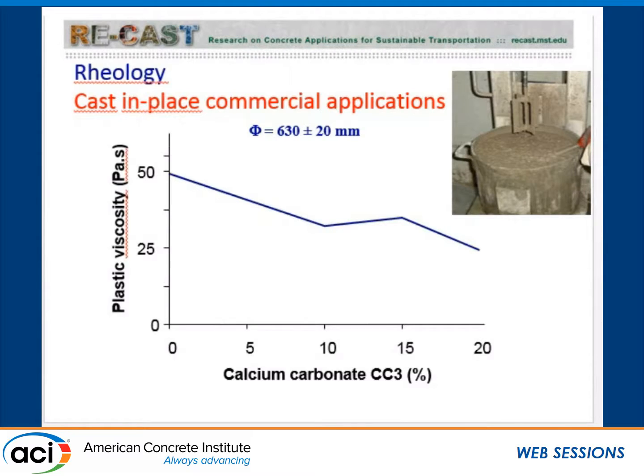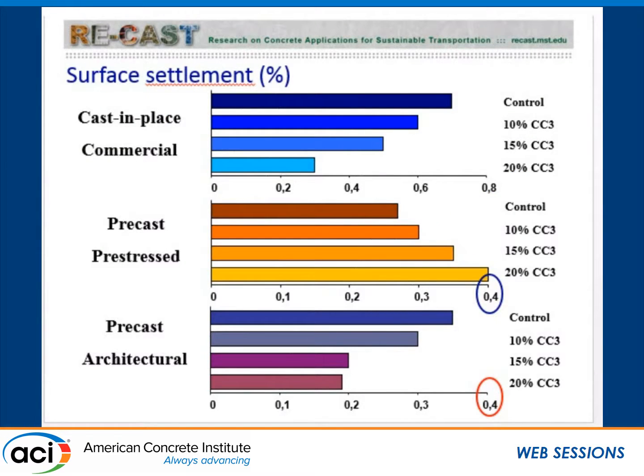But the static stability in this case was very, very good. So surface settlement with the replacements of Portland cement of 10, 15, 20%, we see the settlement is improving quite a lot. So that's excellent. And that has implication on durability, on the bond with rebars. So it's not only a fresh property, it has implication on the... So this is with type 1 cement.